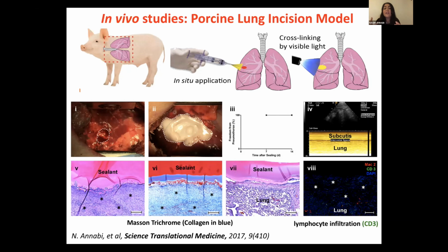And then with this, we confirmed that we did experiment on 6 pigs, and our data show that we can have proper sealing and some degree of tissue healing and regeneration once we apply this surgical material on the defect. So this was done in collaboration with Beth Israel Hospital in Boston. And when we moved to UCLA, here I work with great colleagues at UCLA Medical School.